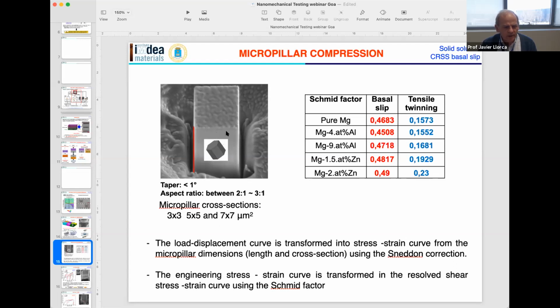And we carved micropillars with different cross sections, 3 by 3 microns, 5 by 5 or 7 by 7, to study size effects. All these micropillars were carved in grains that were suitably oriented for basal slip. So this is the orientation of the crystal within the micropillars. Of course, these are single crystals.